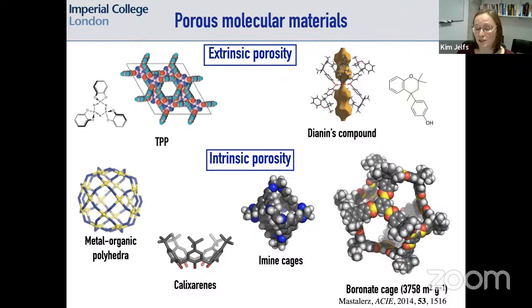This is really quite a rare feature. Nature abhors a vacuum and generally will do a quite good job of managing to pack at quite high density so that you don't have voids. But there are some examples of this, and a real classic example is Dianin's compound, termed by Barrer, the grandfather of zeolite chemistry, so to speak, as an organic zeolite. And that compound has those hourglass shaped channels running along one dimension that can actually absorb some guests within them, from very small gases. And then separately, you have intrinsic porosity at the bottom, whereby the molecule itself has some sort of internal cavity or concave shape, such that it has its own void space.